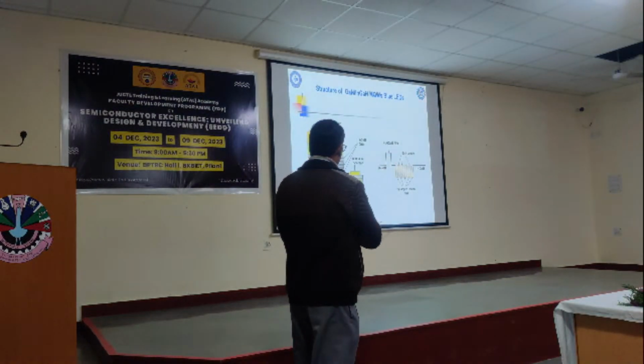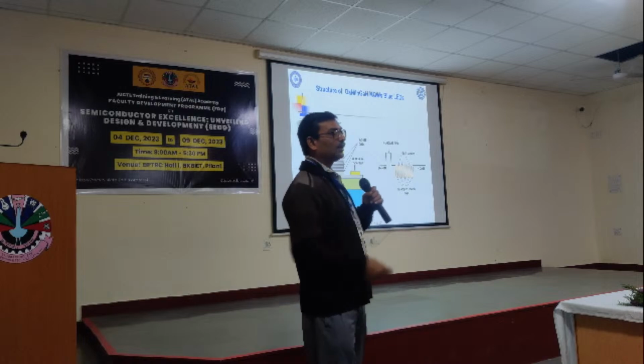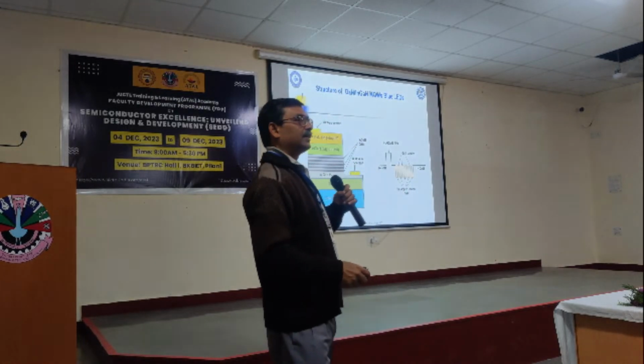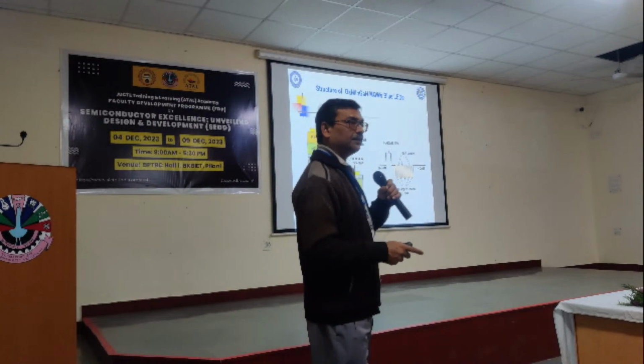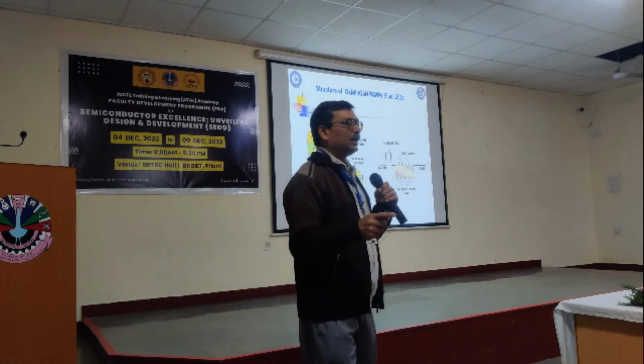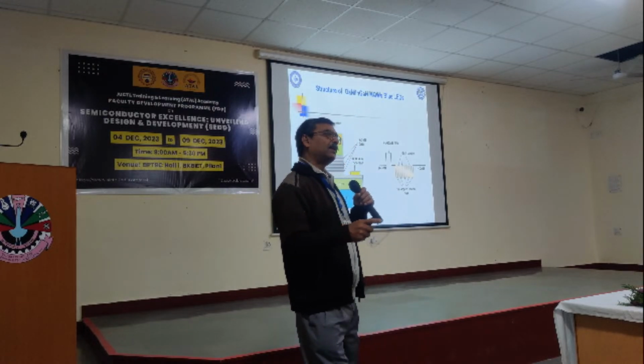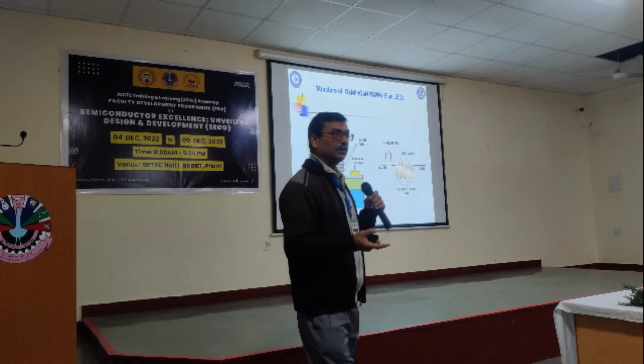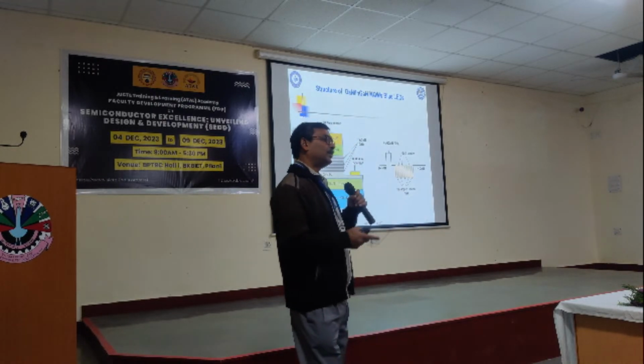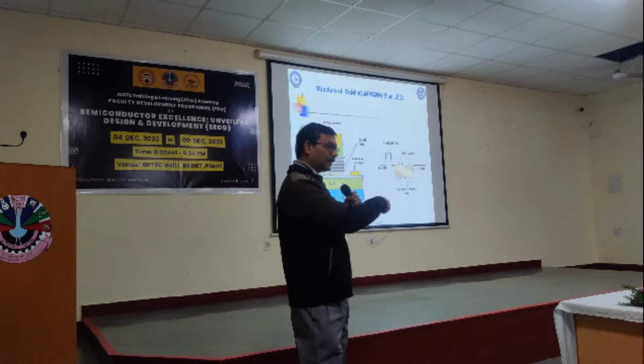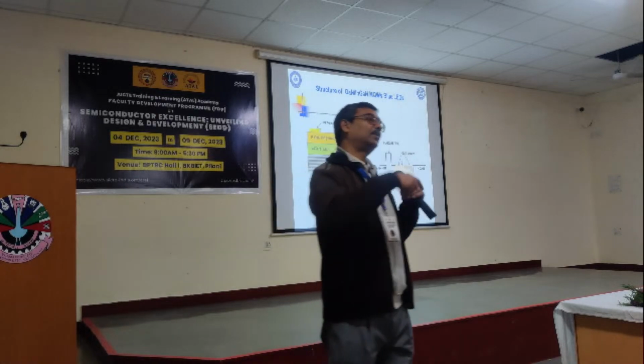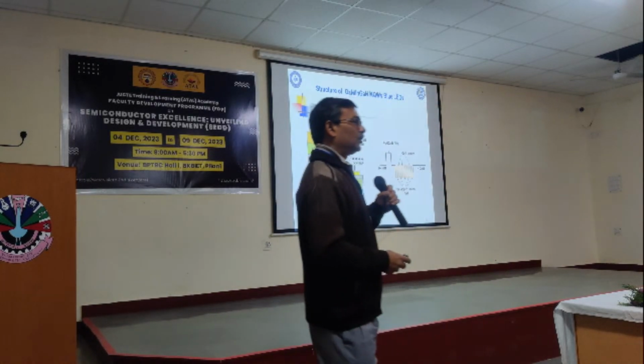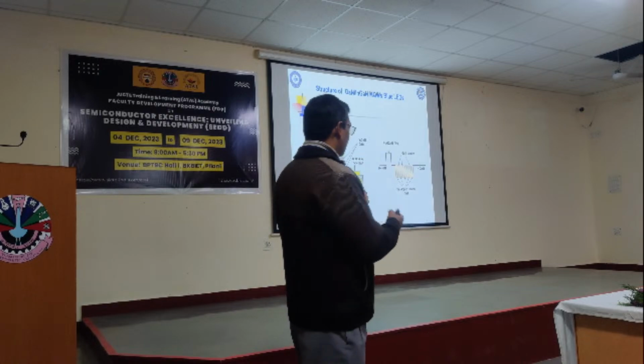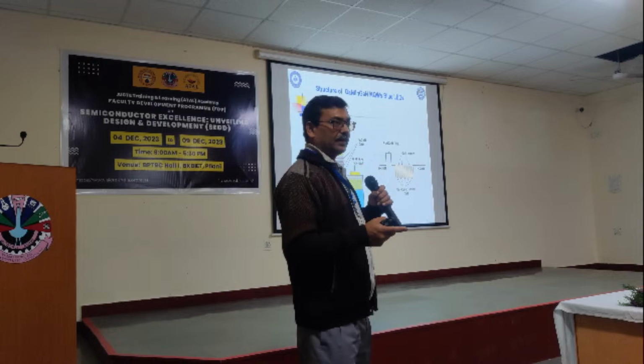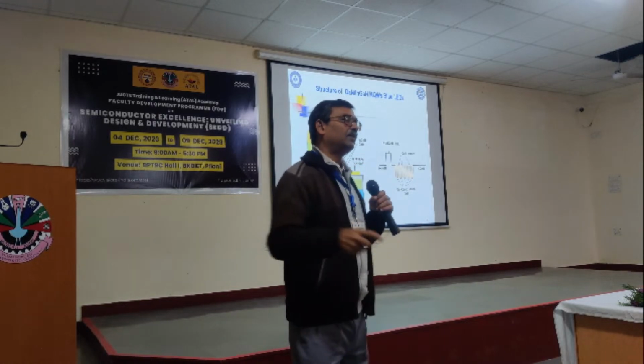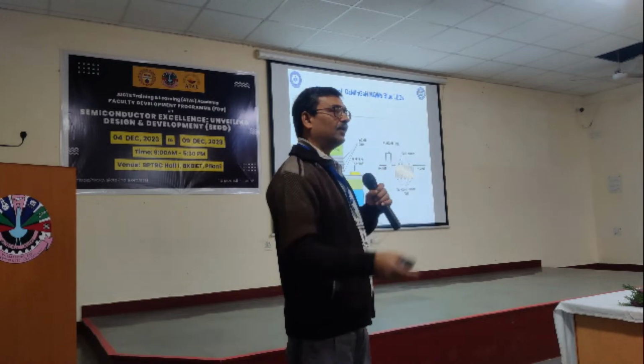On top of C plane sapphire, if we grow the gallium nitride material, it has spontaneous polarization, or is piezoelectric. If we grow the material on top of M plane sapphire, it is quite non-polar, so the polarization property of the gallium nitride material might be less. So for various applications, we have to select the substrate. But again, the cost matters. The C plane is very cost effective compared to the M plane or A plane.